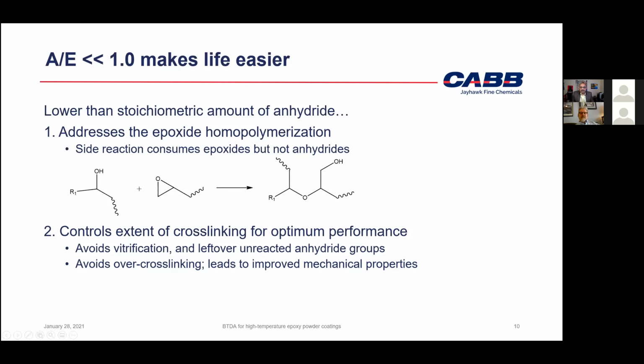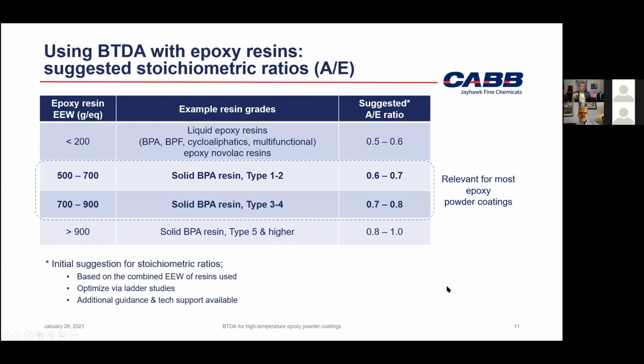So here's the next slide, which we use to give an example of what kinds of stoichiometric ratios to use for different kinds of resins. Obviously, the shorter the epoxy resin molecule, the shorter the equivalent weight, the more off ratio you will have to go, basically more anhydride starved you'd have to go. So in most cases for powder coatings, if you're using EEWs of 500 to 700, 700 to 900, we'll say go instead of 1.0, use 0.6, 0.7, 0.8, those kinds of ranges. And basically, again, what we're saying is if you calculate by pure stoichiometry, you get an amount of anhydride to use with your resin. But we're saying use 60% of that or 70 or 80% of that for your epoxy resin.